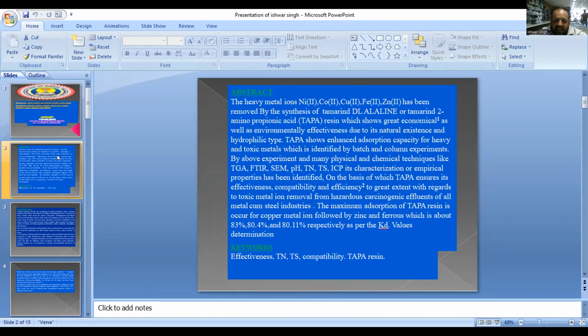I used some chemical techniques like TGA, FTIR, SEM, and pH studies, and tested the removal of heavy metals from wastewater or industrial effluents to check the effectiveness of this resin. It was found effective to a great extent for toxic metal ion removal from hazardous and carcinogenic effluents. The maximum adsorption of this TAPA resin occurs for copper, approximately 80%. This was calculated by KD value determination.